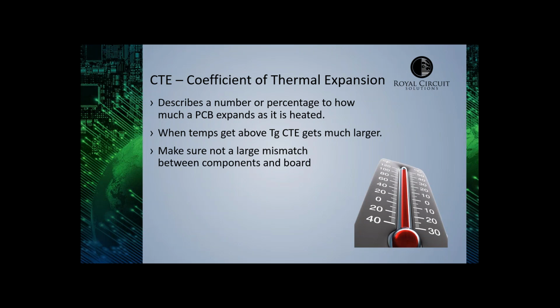The other thing for this that you want to worry about is a mismatch between the components and the board itself. So the obvious example is silicon chips have a very low CTE. And if it's much lower than the board and the board is heated, the board will expand faster than the component, and then the solder joints can weaken and break. So you have to look at your components as well and how they act if you're submitting your board to some pretty high temperatures.